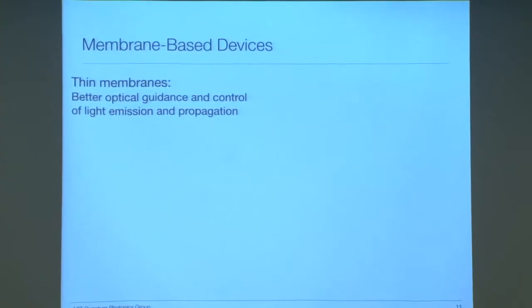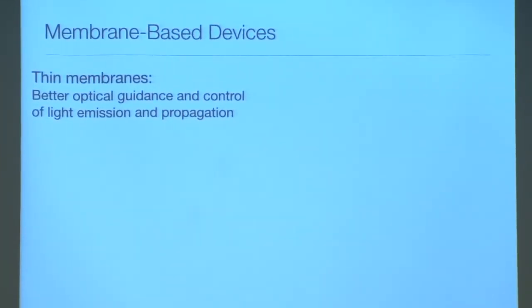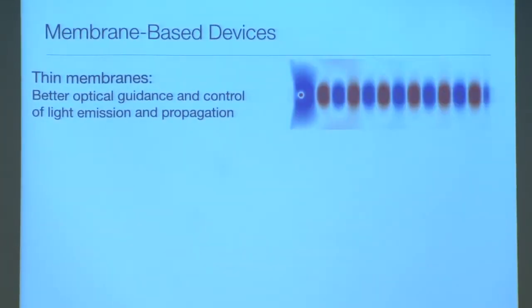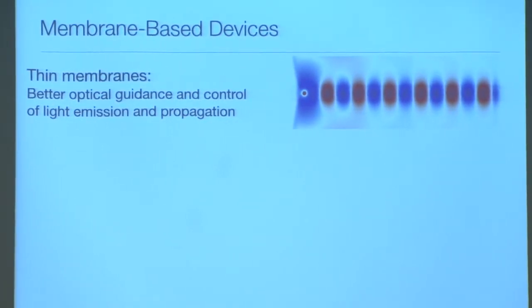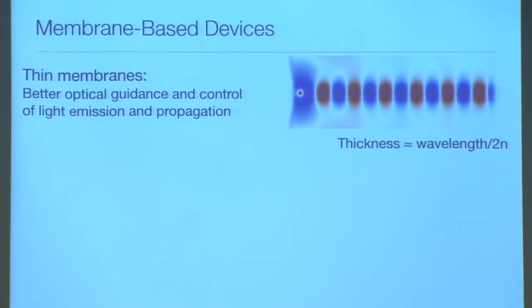In thin membranes, optical guidance and control of light emission and propagation is most straightforward. And in this image, you can see a dielectric membrane. This is a mode pattern of a dielectric membrane with a simulated continuous wave plane wave source at the left end. And the thickness of this dielectric membrane should be on the order of half of the effective wavelength to achieve single mode guidance.